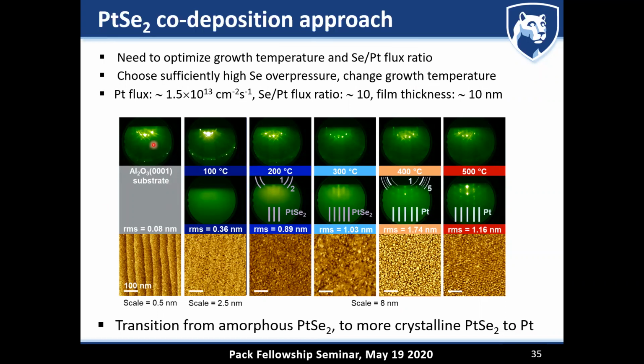And so what I'm showing you here are some RHEED images that we've taken from the substrate. The substrate we're using is sapphire. And you can see as you carefully increase the growth temperature from 100 to 200, 300, 400, all the way up to 500, you indeed form platinum diselenide, but this RHEED doesn't look that great. There's a hazy background indicating that you have an amorphous film. There is at some point some polycrystallinity. You see these diffraction rings. Overall, if you're an MBE grower, that's just not good.